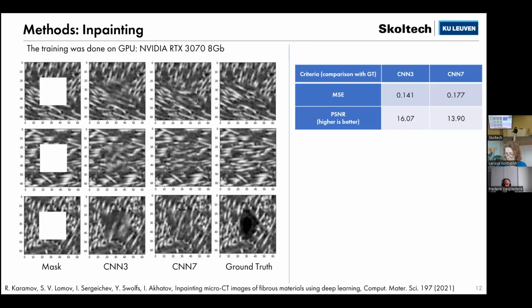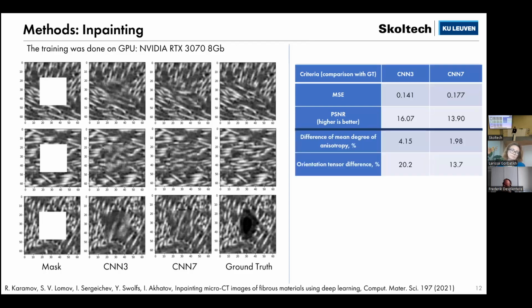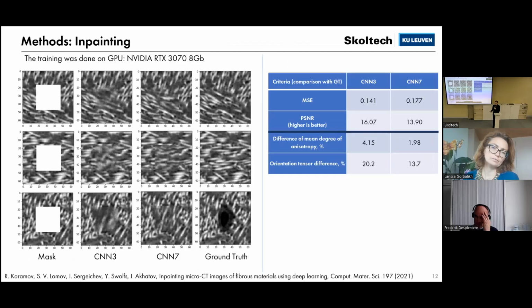And if we move to the metrics, you can see the image-related metrics are better for smaller neural networks. But if you move to the material-related metrics, for example anisotropy and orientation of fibers, we can see that deeper neural networks give us much better results. This is due to the fact that CNN3 relies more on the image-related metrics, but it doesn't generate new data. It just wants to make the image look as close as possible to the original one.